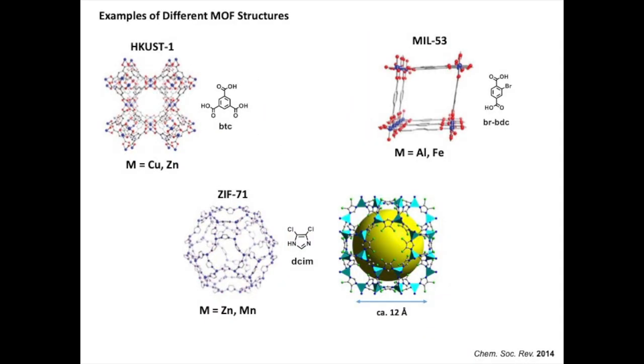For example, this is a linker, benzene tricarboxylate, which in the presence of copper or zinc could lead to this structure known as HKUST-1. In this case, we can actually make MOFs out of aluminum or iron using the linear linker, or we can use an imidazole-based system using zinc and manganese and come up with a metal organic framework. This is another representation showing the yellow sphere that depicts the empty space in these materials, so that a gas molecule could diffuse into the pores.